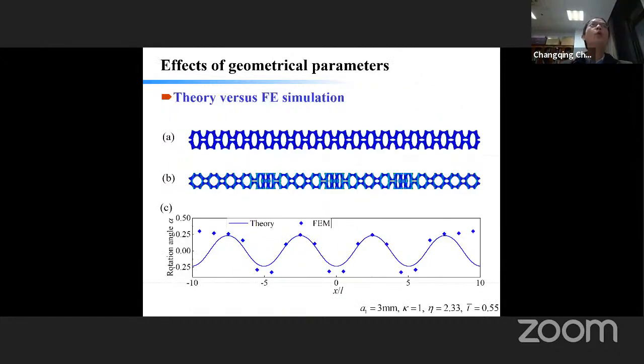So now we want to go one step further and verify the theory. As I mentioned previously, we already compared the parameters and the experiment result with our theory, but now we are going to a different set of geometry. We want to check the predictive capability of the developed model by using a different set of geometry parameters. Again, you can see here is the theory and here is the experiment, and we are able to achieve quite a good agreement.